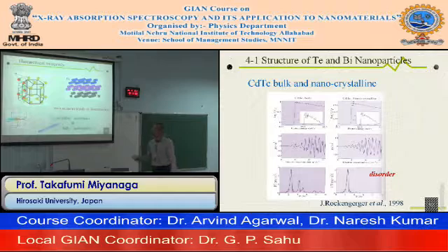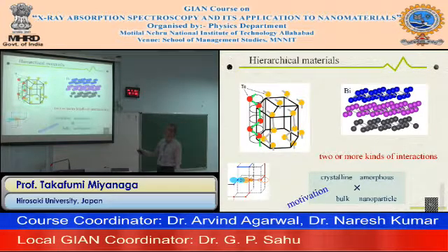Now, we call this type of material hierarchical materials. The reason why it is hierarchical is that the first order structure has very strong covalent bonding making the chains. And those chains are gathered for the trigonal crystalline and make a three-dimensional crystal. Analogously, bismuth has a strong three-fold covalent bond, making a two-dimensional sheet, and three-dimensionally these sheets are stacked, and show very interesting electric behaviors, the semi-metals.